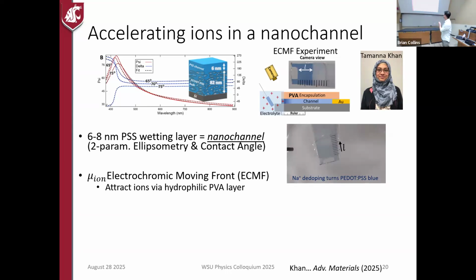So what we did was we made these devices. Here's the PEDOT:PSS channel. We dip it in water, actually electrolyte with sodium ions, and we force the ions to only go in at the end of the channel by putting on an encapsulation layer, so it's water impermeable. And we put a voltage between the electrolyte and the gold on the other end of the channel to drive the ions into the channel. What happens is the ions go in, and I said that the PEDOT and PSS are joined with an ionic kind of bond. Well, when the ions come in, they replace the PEDOT. They separate those two out. And the PEDOT goes from being transparent to blue. That's electrochromism. So wherever the PEDOT is blue, we know that's where the ions went. We use the color to tell us where the ion goes.